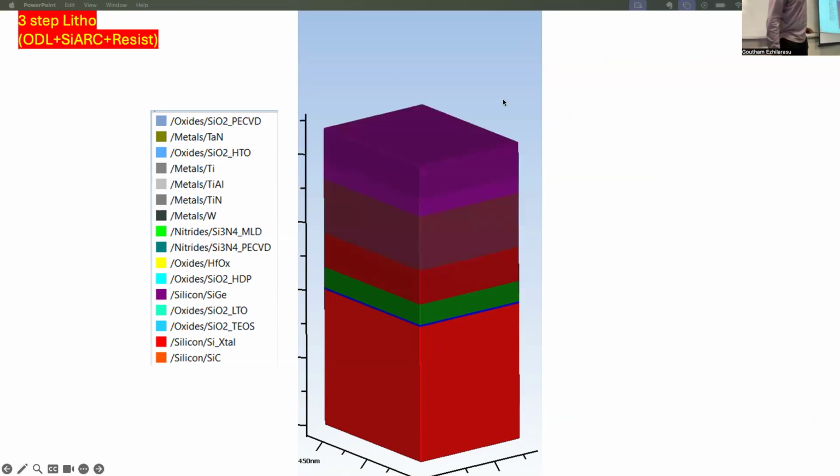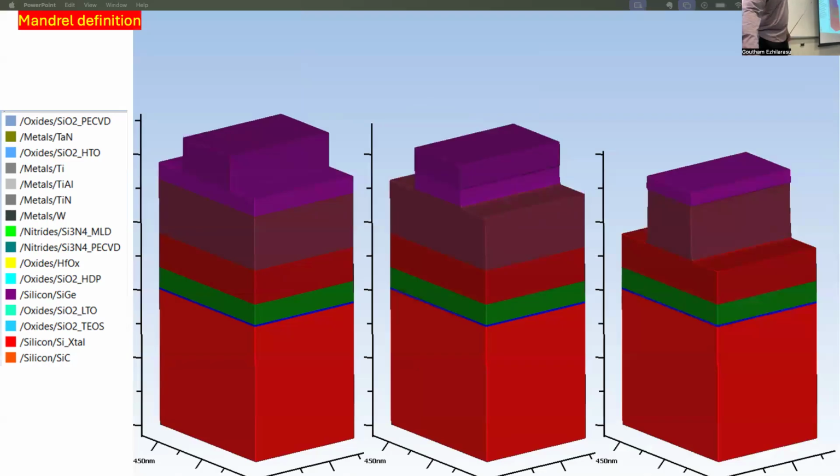And so the next step is, you need to define your polysilicon mandrel, right? For that, you have to pattern this. So you need a tri-layer resist: the ODL, you remember the optical planarization layer, then the anti-reflection coating, and then a resist. On top of this, you do your lithography. This is the first mask for defining your mandrel.